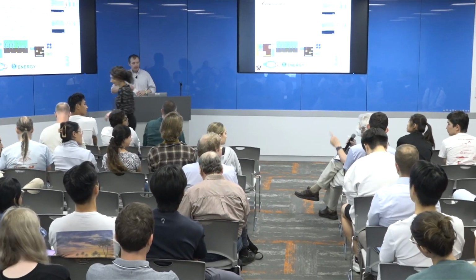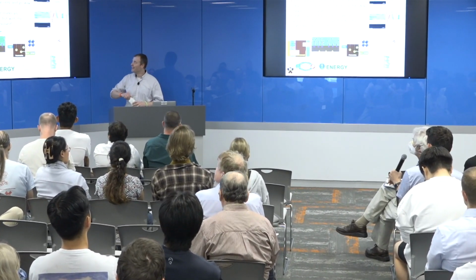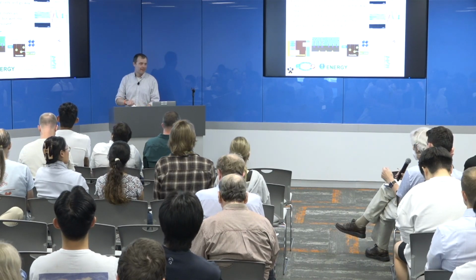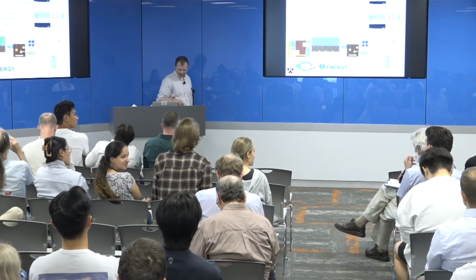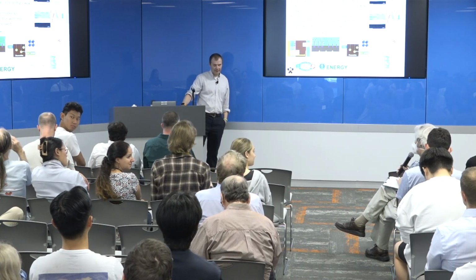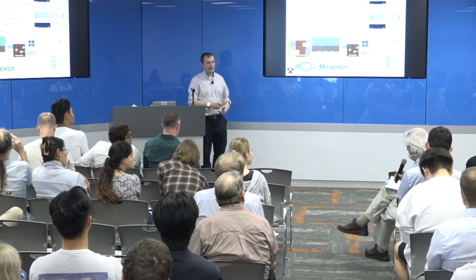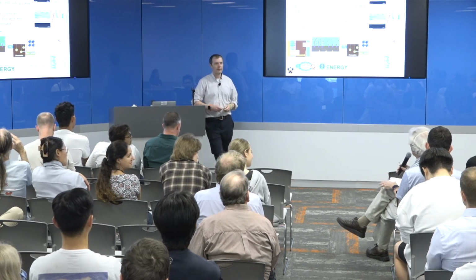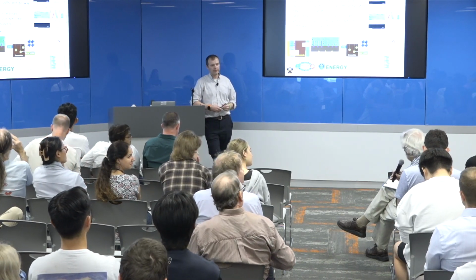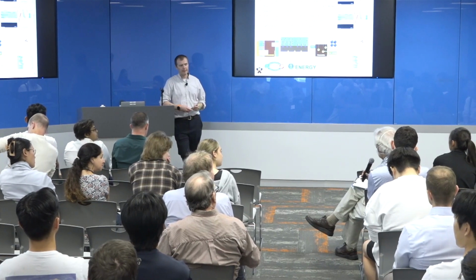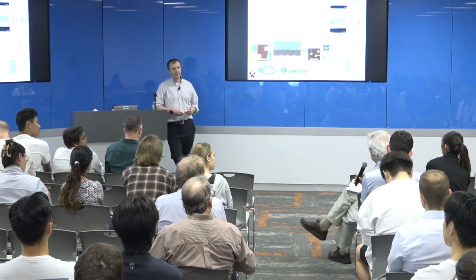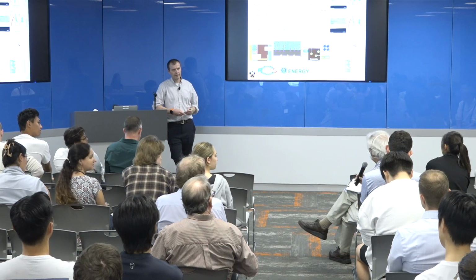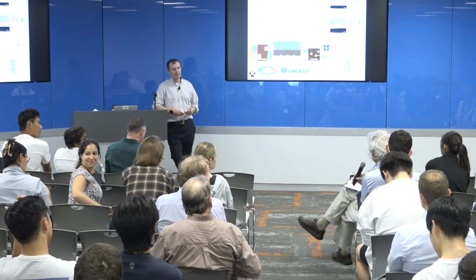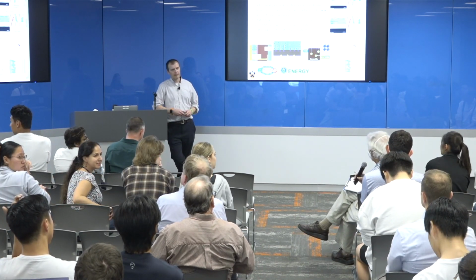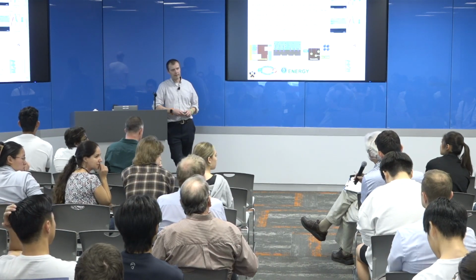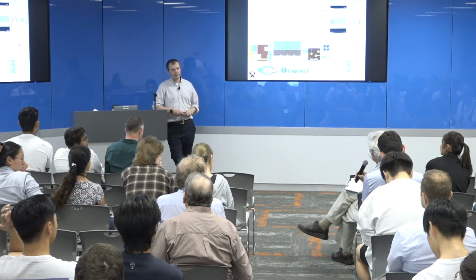I'm going to take you up on the first point there, that they go way beyond ion migration. Fifty years ago, I did a lot of work in alkali halides, not perovskites, trying to dope them with excess halogen. That was done principally with potassium iodide doped with iodine under extremely high pressures. And one gets the same interstitial type populations that one does with the radiation of alkali halides.